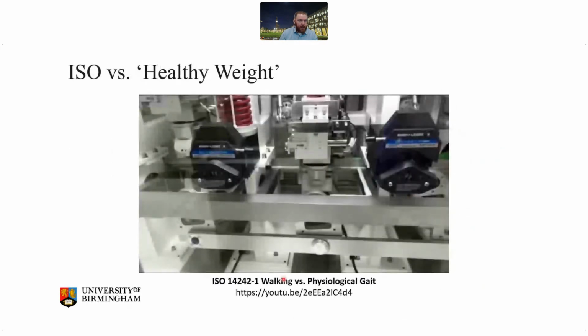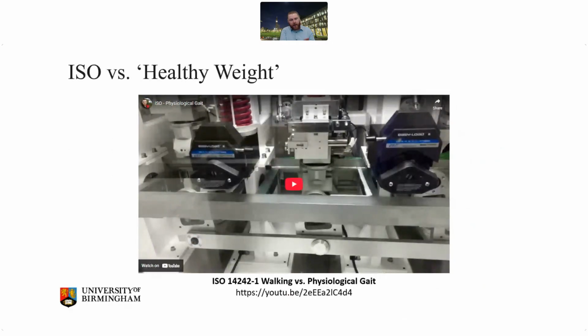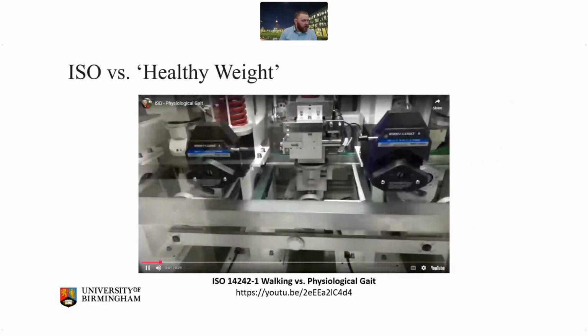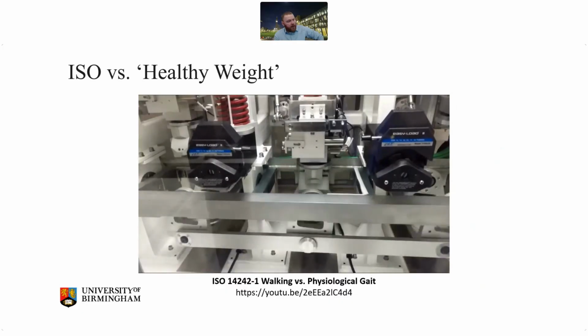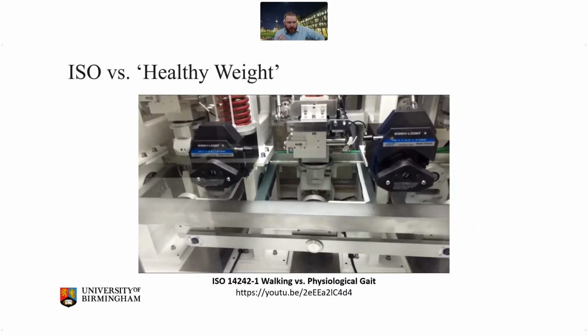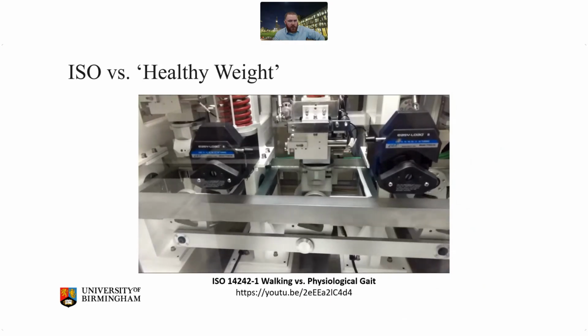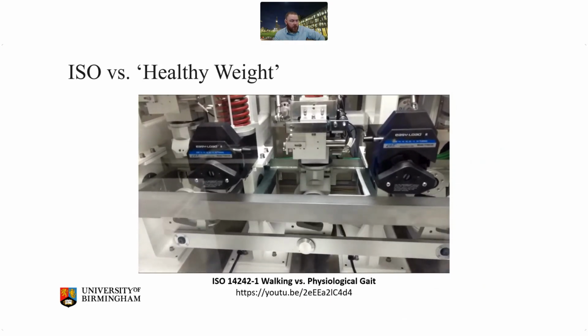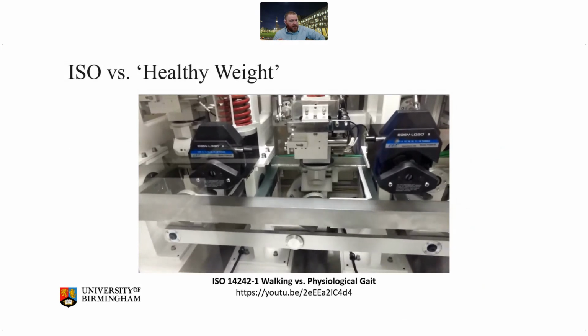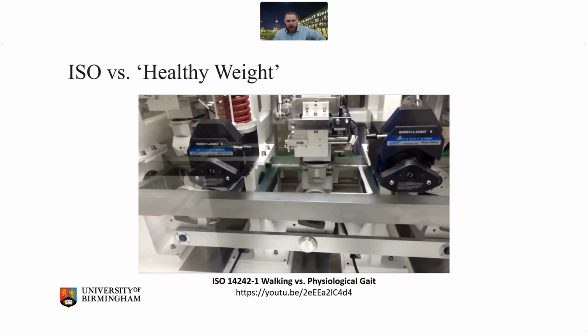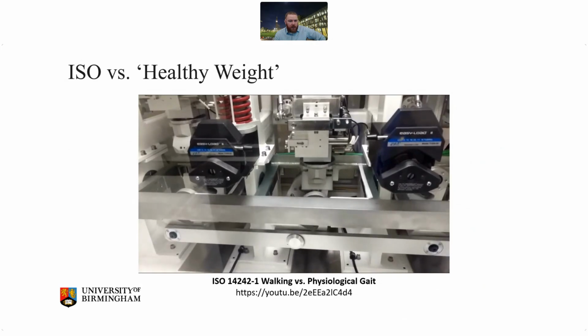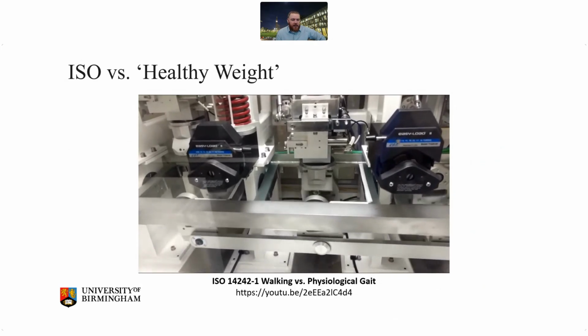So I have a video here just to demonstrate that. What this video is going to show you is the simulator running through 10 cycles of the ISO walking profile, and then 10 cycles of the healthy weight physiological gait. So I'll just get that started. And what you'll hopefully hear is, this is the ISO profile, just those sine waves. Sounds fairly sedate, but when we switch to the physiological kinematics, it's just much more abrupt in that turn. The loading is very different. The kinematics are very different, and that translates into the wear rates.